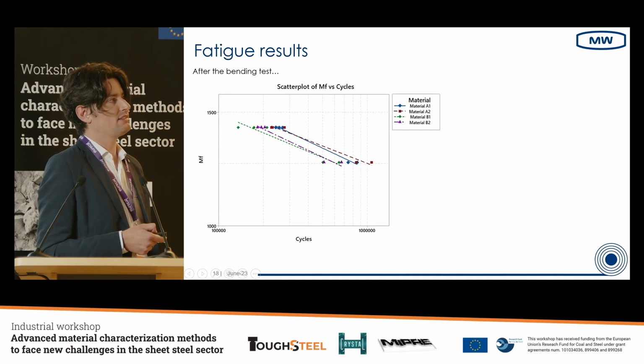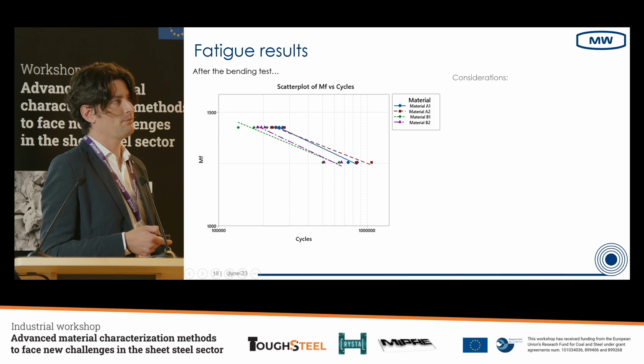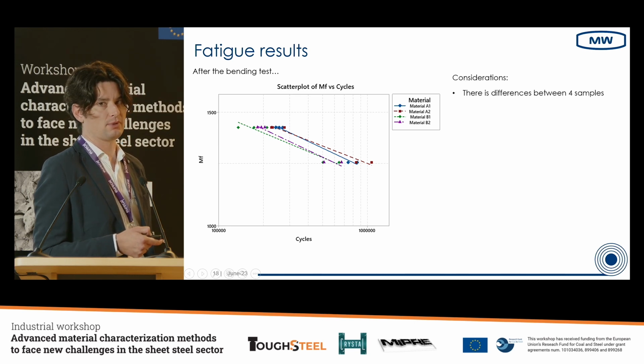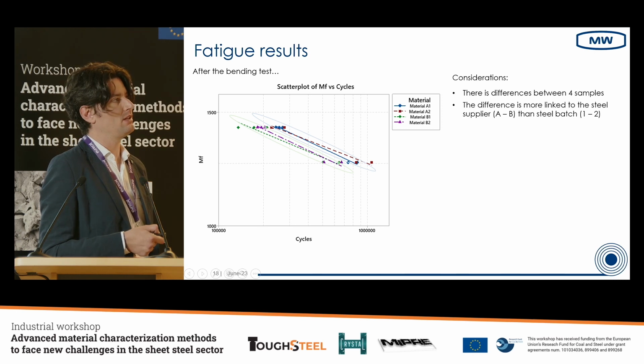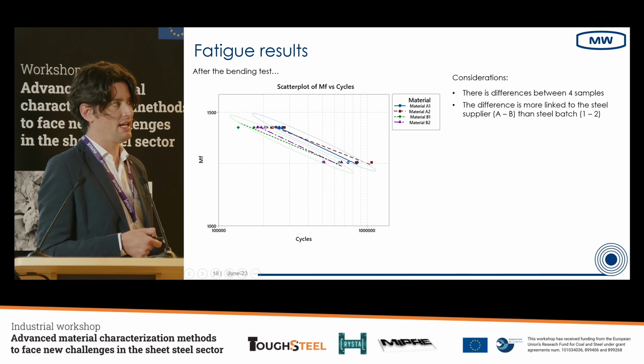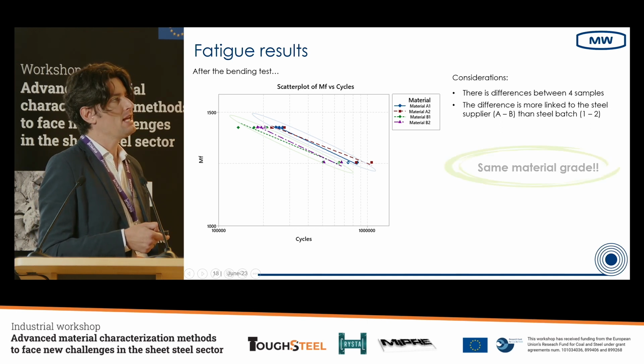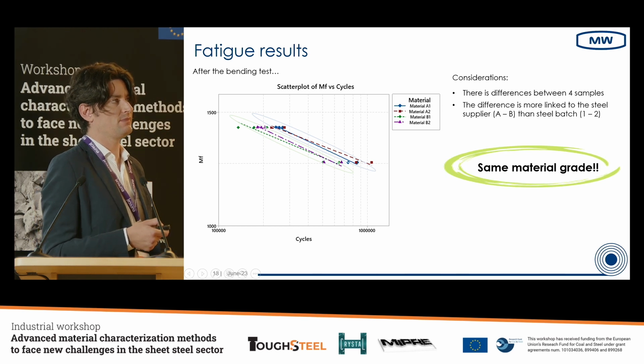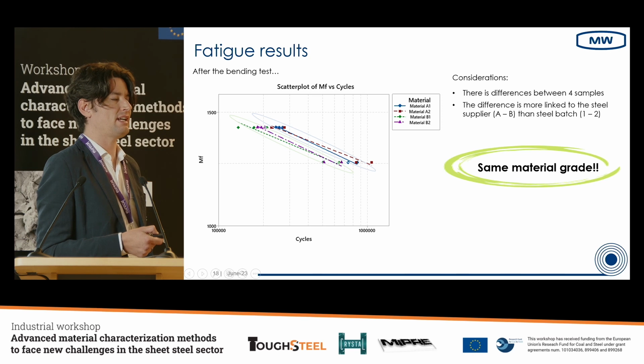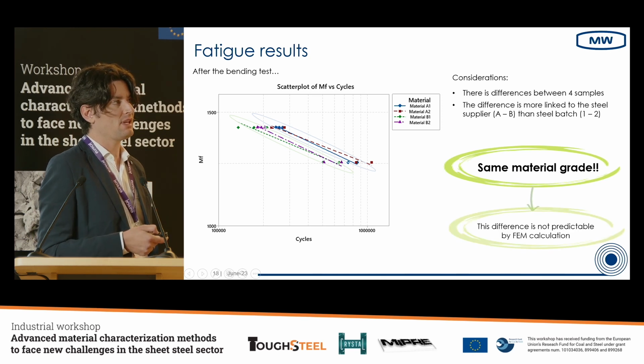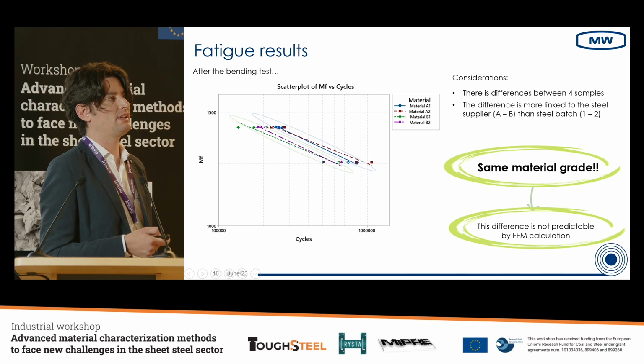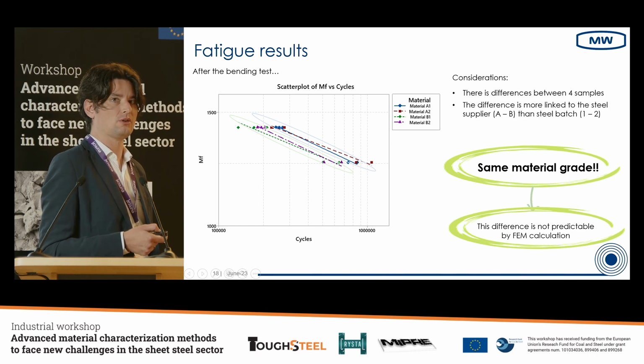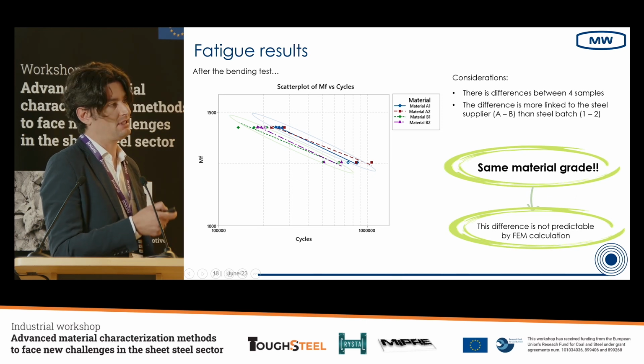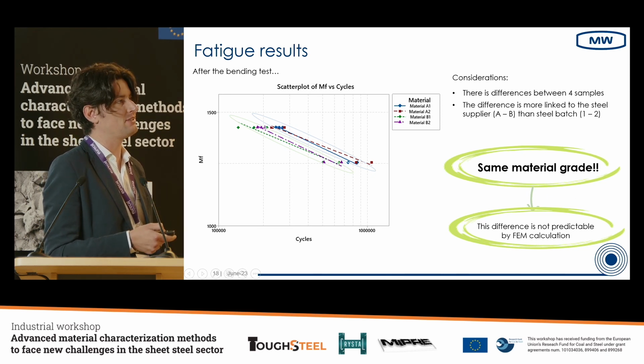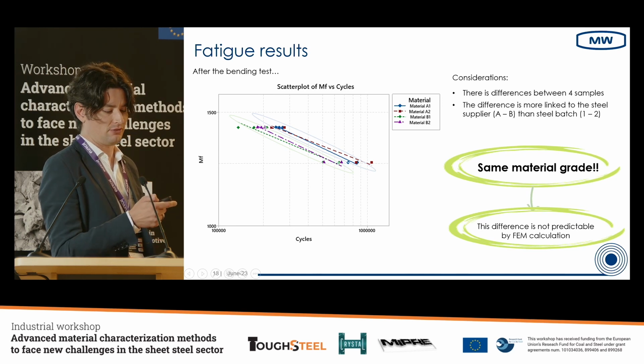Okay, these are the fatigue results. As is visible, there is a difference between the 4 samples, especially between steel supplier A and steel supplier B. There is not much difference between the 2 different batches. But these discs are made with the same material grade. And this is a problem because for the simulation, this is not predictable. So we have just the same material data for the same material grade in the simulation, but we see that there is a difference.